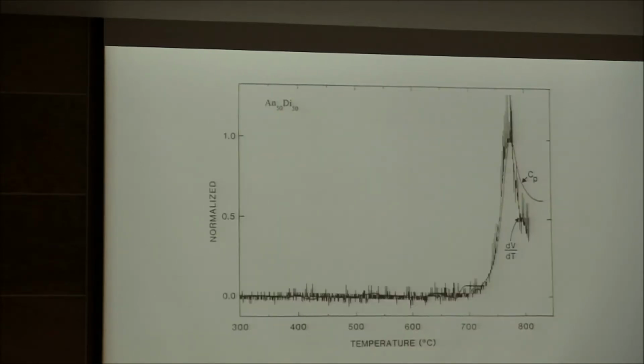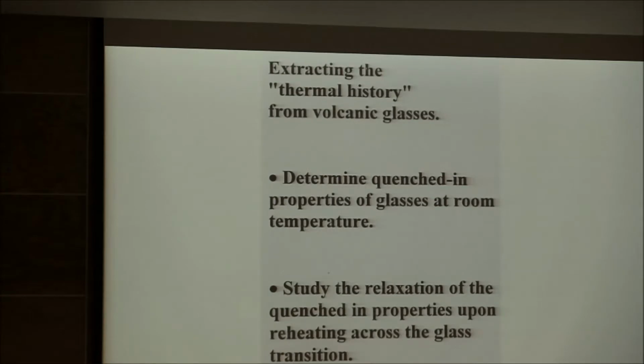Okay. This is an example of the fact that no matter how you measure the glass transition, you always get the same result. So the peak here refers to the glass transition. And you see here, it's a CP, it's measured with a calorimeter. But actually here you see dV/dt, volume versus temperature. It's obviously not measured with a calorimeter, it's measured with a dilatometer. It's something which is measuring the dimensions of the sample, and yet it gives exactly the same results for the glass transition. All of these things, all of the properties that can be used to measure the glass transition, they all fall back to one value of glass transition, because it is the viscosity and its temperature dependence which is controlling the glass transition.